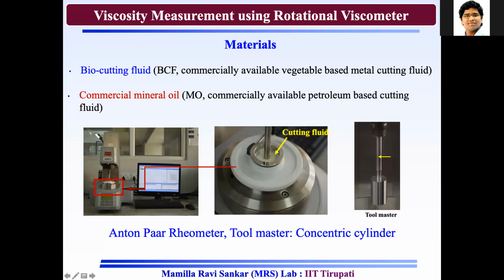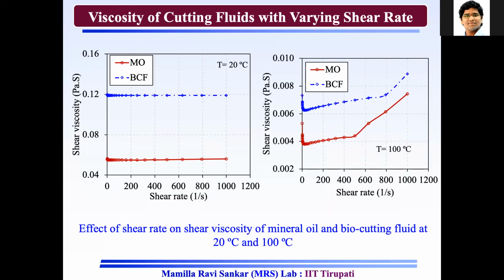As you can see, the cutting fluid is filled as per the guidelines of the rheometer, and this is the tool master, the concentric cylinder tool master. If you see here the shear viscosity, normally you are doing a shear test, so you also observe the shear viscosity versus shear rate. How to measure shear rate and other things you will see in the upcoming slides for abrasive fluids.